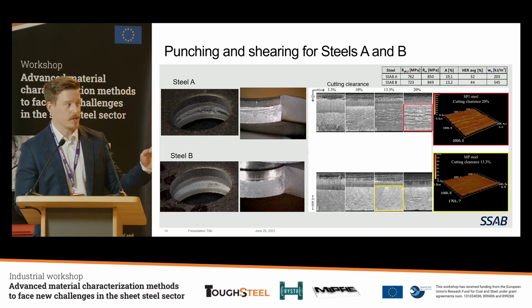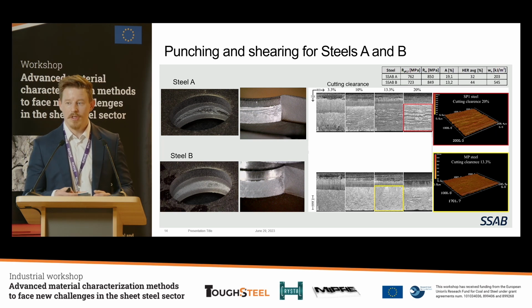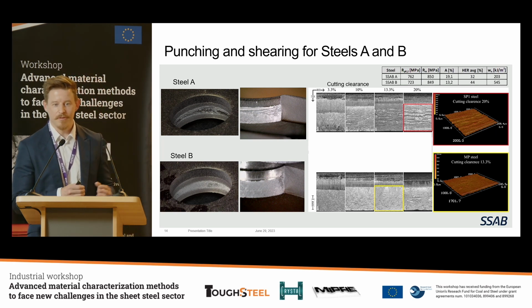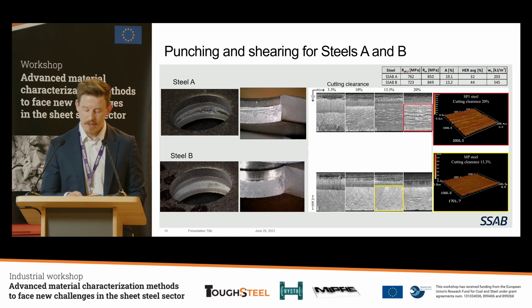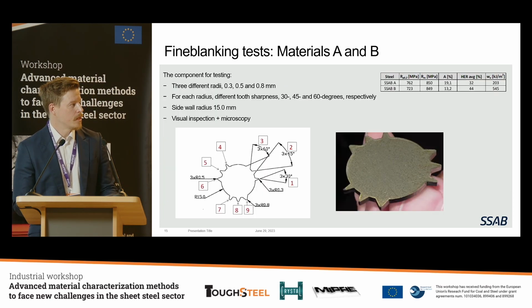And actually, the only thing that we could say is that this material B is showing a much higher level of essential work of fracture. Of course, we have only 2 steel grades here. Is it a universal truth? But really interesting results. Then fine blanking.